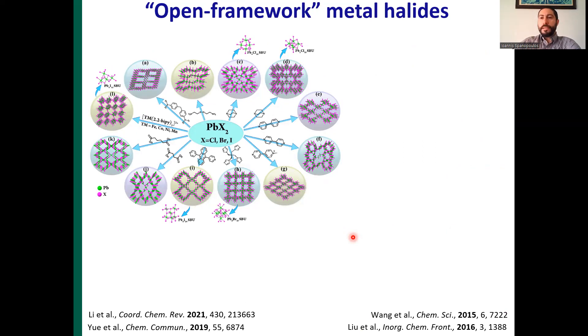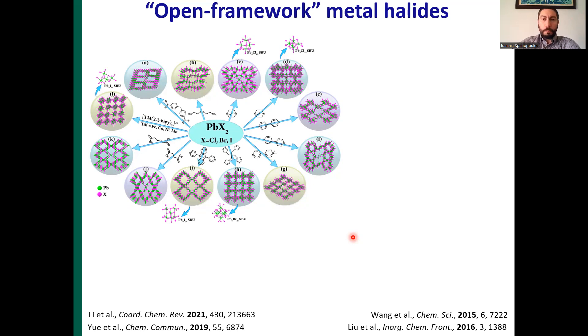These materials feature a combination of traits that cannot be found in any other class of fully organic or fully inorganic semiconductors, such as long carrier diffusion lengths and lifetimes, hard radiation damage tolerance, and solution processability. For these reasons, there is immense effort for the commercialization of these compounds. If we find a way to generate porosity to this important class of materials, this would allow them to be utilized in applications beyond photovoltaics, such as sensing, solid-state batteries, photocatalysis, and integrated waveguides.